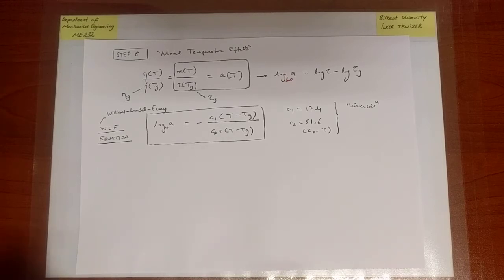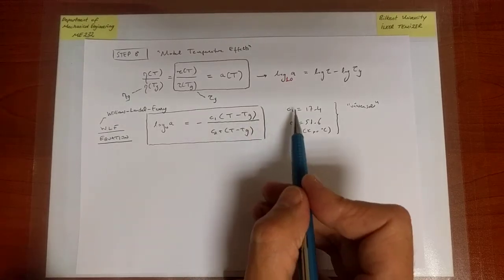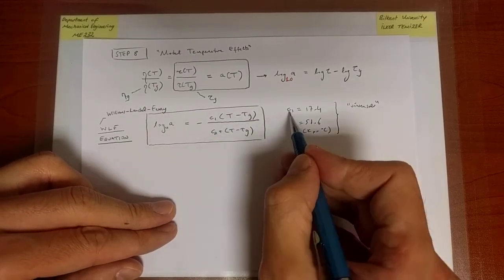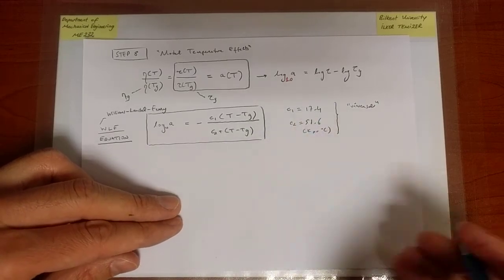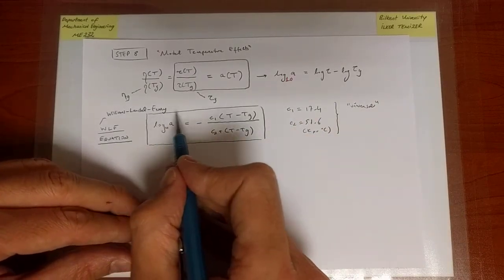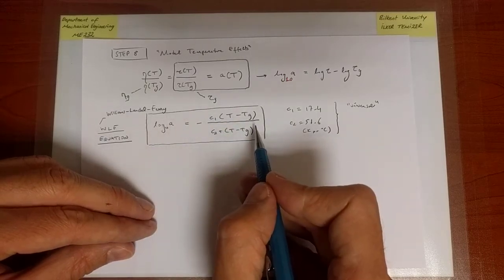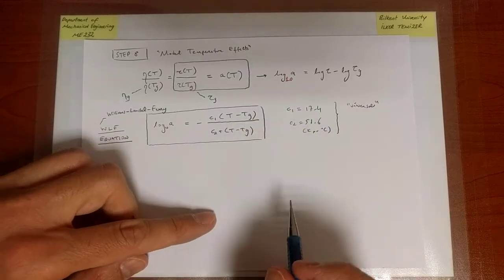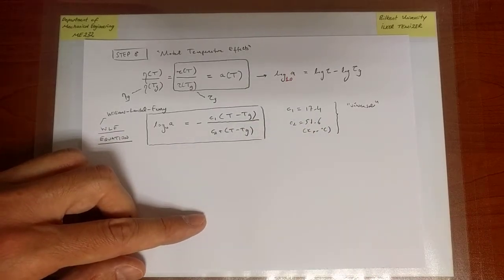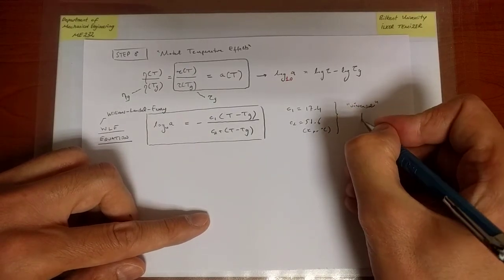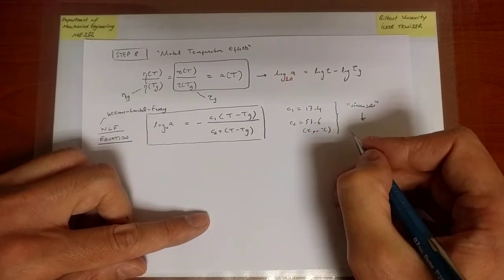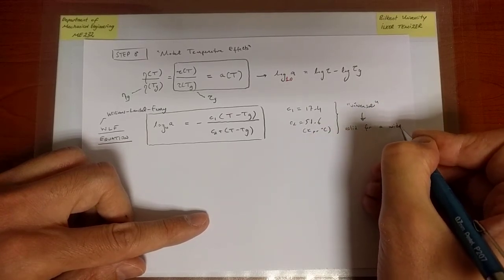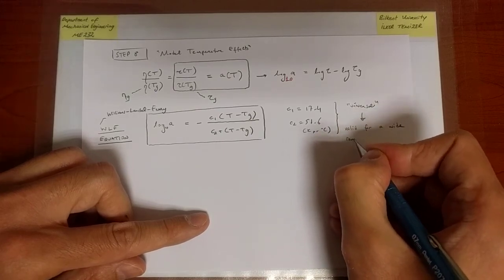Well, you do see a material property, namely Tg, but apart from Tg, these constants do not really depend on the type of polymer you are looking at. In other words, this log A function depends on the type of polymer only, surprisingly, through the glass transition temperature of the polymer. And in that sense, it is universal. So it is valid for a wide range of polymers.